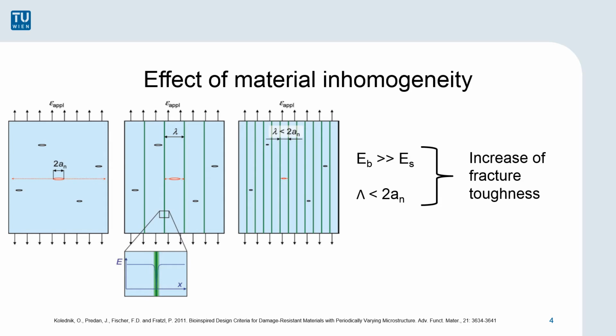Small defects are located inside the sample and statistically distributed. If tension occurs, a crack will start to emerge from these already existing defects. This crack will grow and propagate through the sample until fracture occurs. The same testing procedure is done with a testing sample where thin layers of another material with significantly lower Young's modulus are inserted. These compliant layers hinder the propagation of the cracks and therefore increase the resistance to fracture. As these soft material layers are very thin, they do not change the other mechanical properties of the bulk material remarkably.